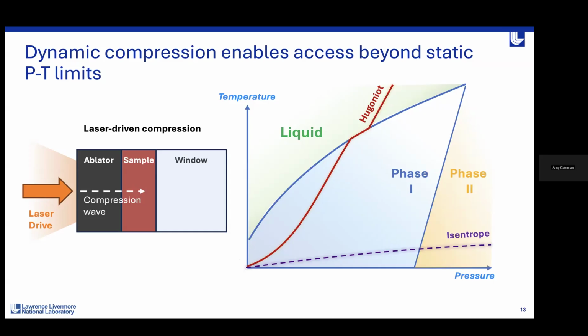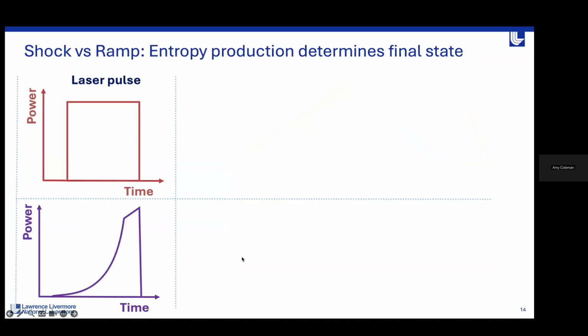The other option that we have quite well developed on hand is ramp compression. And this is a lower entropy process. And as a consequence, the compression path through pressure temperature space occurs at much lower temperatures. And it's represented typically by an isentrope or really a quasi-isentrope. Now, I just want to go into slightly more detail about these two methods of compression before we move on. If you wanted to launch a shock compression in your sample, the pulse shape would look very different from your laser than if you wanted to launch a ramp, right?